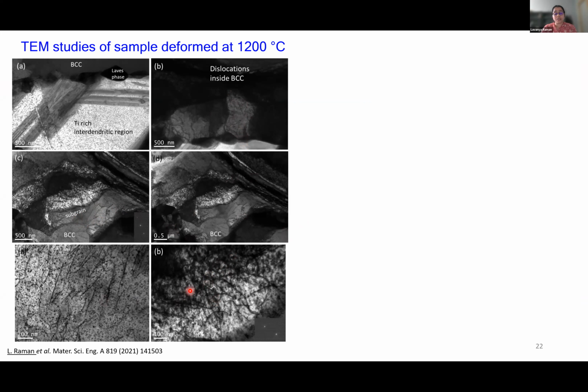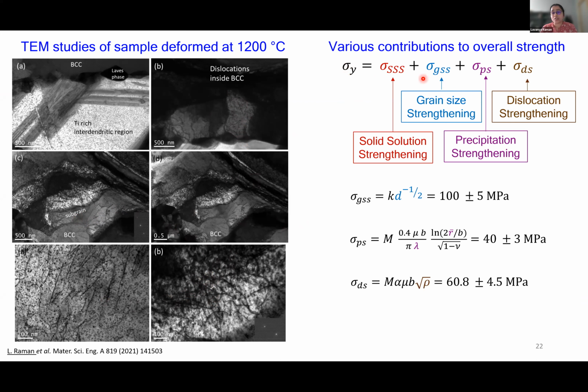So from this dislocation imaging, we tried to understand what is the strength contribution coming from the dislocations. If we go by this equation, sigma y gives us the overall yield strength, and the contribution from different sources can be the solid solution strengthening, which can come from a single phase BCC, the grain size strengthening depending on the grain size of the alloy, the precipitation strengthening, which can be from this Laves phase, and the dislocation strengthening from the dislocations that we observe in the BCC phase.